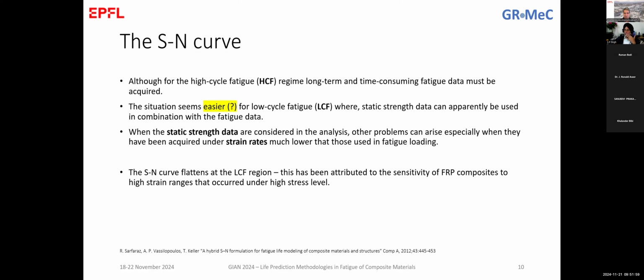It is easier in low cycle fatigue, but it's not necessarily easier because of several reasons. And one is the reason that we already discussed yesterday, and we also spent a lot of time there, is that at high stress levels, we need to fix the material well. So we need to grip the material well. So we need to probably increase the pressure in the grips. And we've seen also because of the high stresses, we have stress concentrations that in several cases lead to a significant number of tab failures. So failures that are not accepted in fatigue analysis. So to respond to this question mark there, at high stress levels, it is faster to do testing, but it's not a guarantee that it is also easier to collect an appropriate number of valid test results for low cycle fatigue.